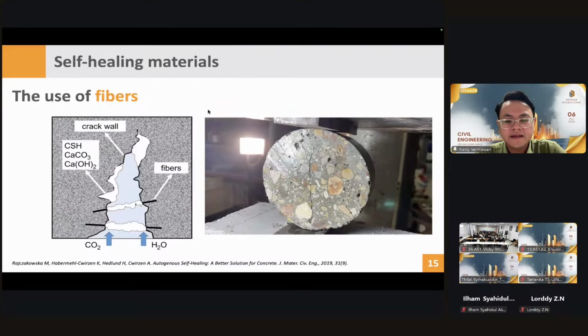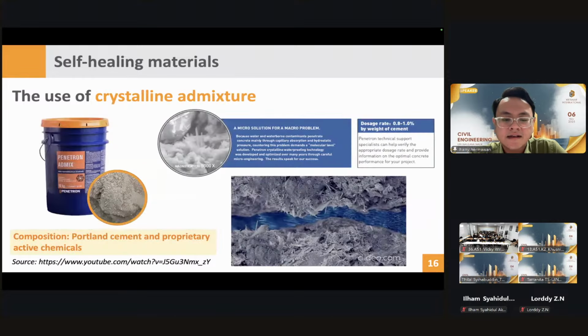Next, we also have a very innovative material so-called crystalline admixture. So this crystalline admixture is composed of the Portland cement and proprietary active chemicals. If you look now from my slides, I also show a picture of the crystalline admixture. It looks like a cement because the color is a bit gray, but there are some white particles contained in this material, and these white particles are the active chemicals that will work as a self-healing agent.